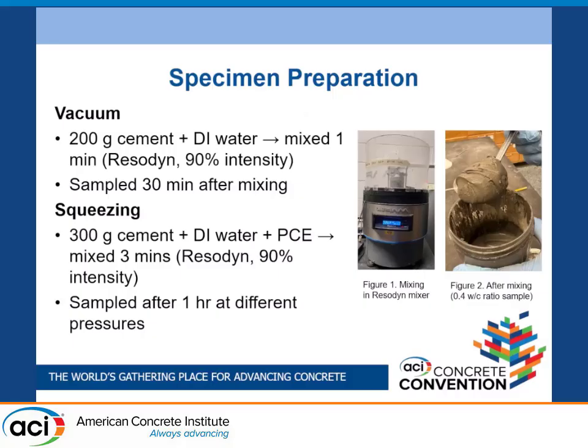It's a very simple test. In the vacuum method, we are using 200 grams of cement with deionized water, and those samples were mixed for 1 minute in a Resodyne acoustic mixer at 90% intensity, and sampled after 30 minutes. Then for squeezing, we are using 300 grams of cement.